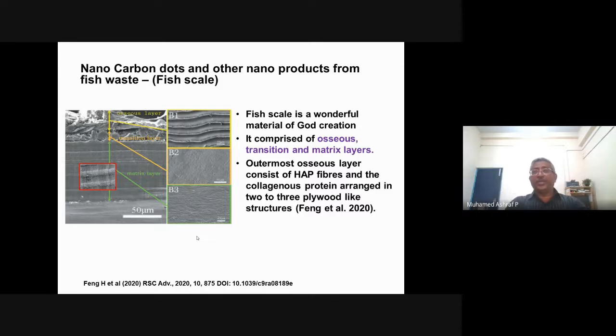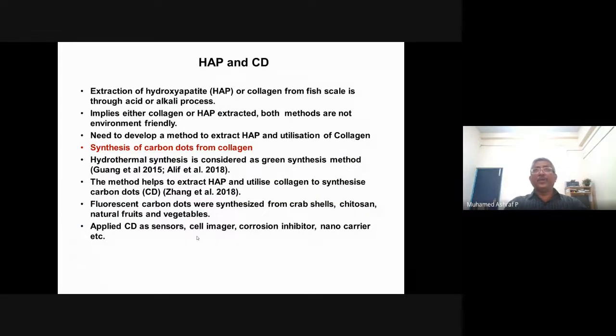Also, what we have done is use fish scale. Fish scale is rich in collagen and hydroxyapatite. The fish scale is a wonderful material. It is a wonderful creation of God, actually. It is comprised of osseous, transition, and matrix layers. These are the three layers present in the fish scale. The outermost osseous layer consists of hydroxyapatite, and collagen is a protein arranged in two or three plywood-like structures. Whenever we extract hydroxyapatite from the fish scale, the procedure is a highly acid or alkaline environment. What will happen is only hydroxyapatite will be obtained and you will lose collagen. Otherwise, if you are thinking of extracting the other one, you will lose the other fractions, like part of the hydroxyapatite and calcium derivatives.